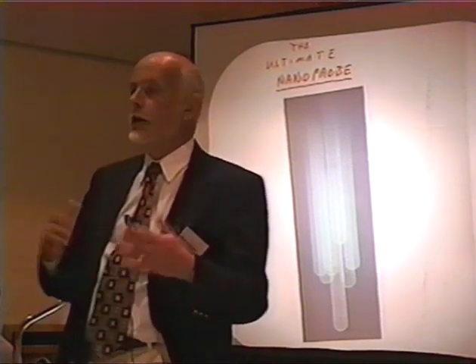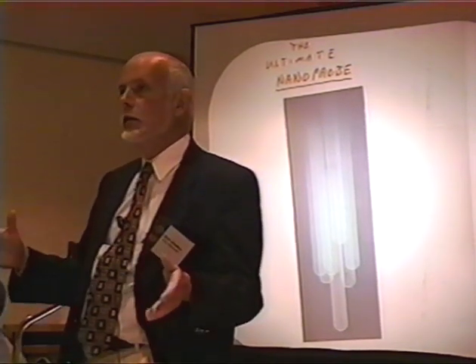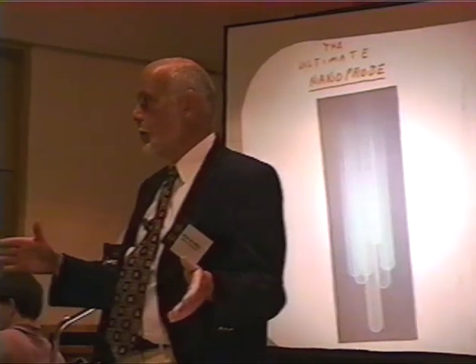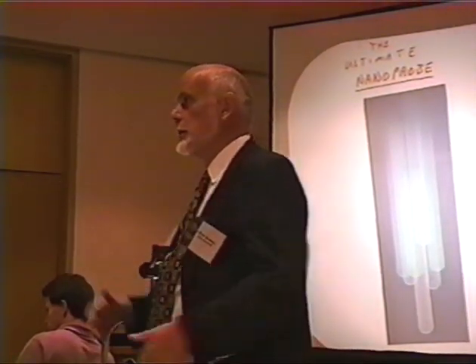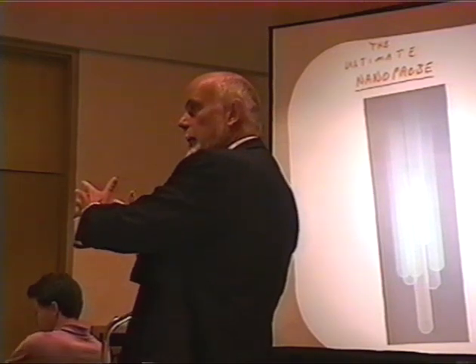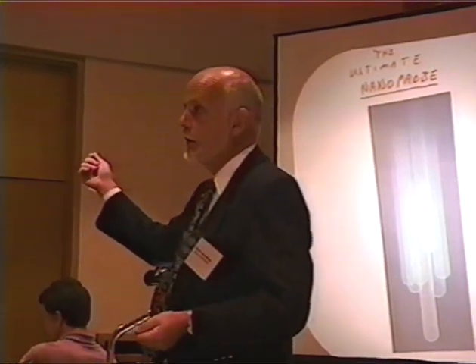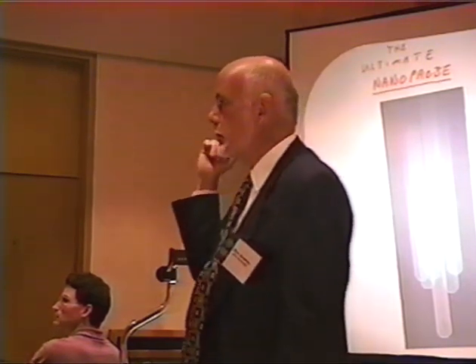If you look at the history of graphite fibers, it's been a series of small, minor revolutions, where at each stage the fiber has had the graphene sheets more aligned along the axis. But this is the end point. And rather than using 2,000 to 3,000 degrees centigrade to do it, you use a catalyst and you make a molecule. And it keeps on being perfect because the only place there's a very active edge is right at that lip. And thermodynamically, what you want to make is so much better than anything else that that's what's made. But yeah, this is the same deal. It's a question of how you nucleate it.